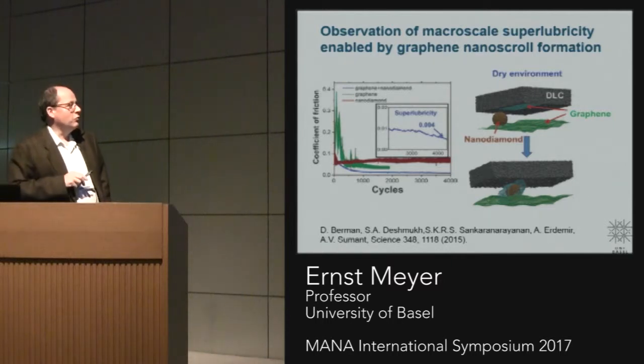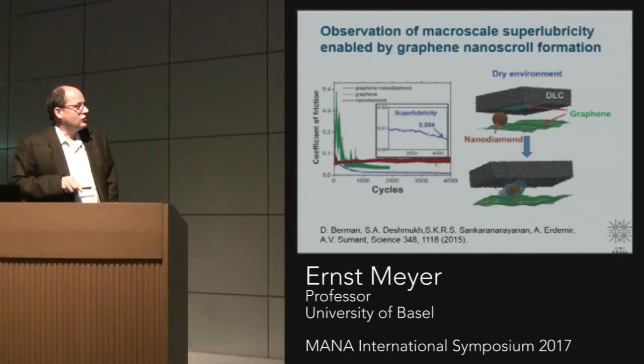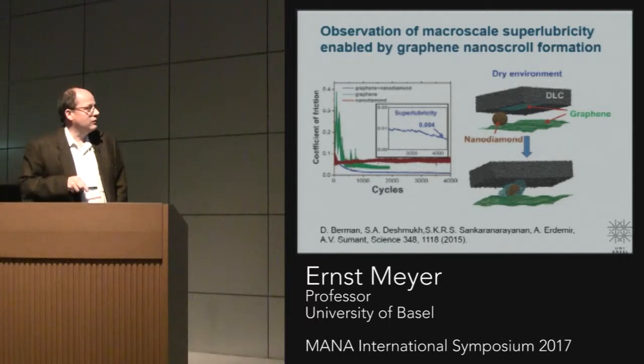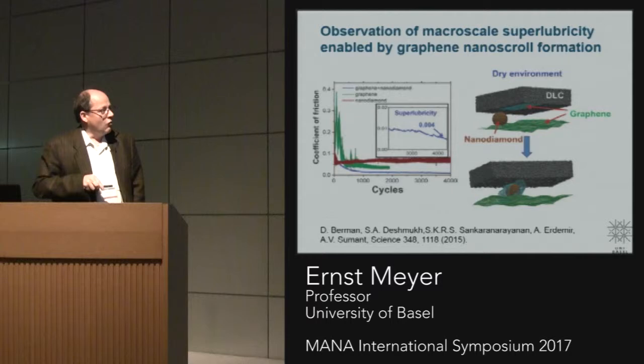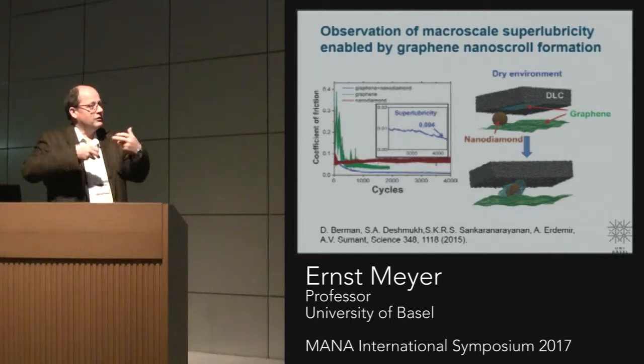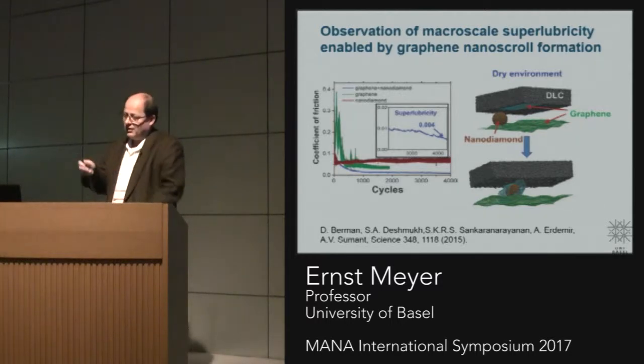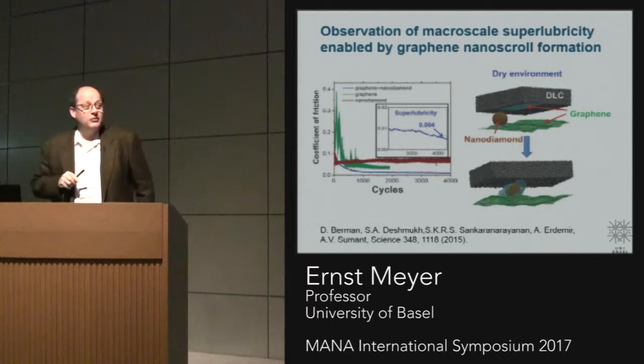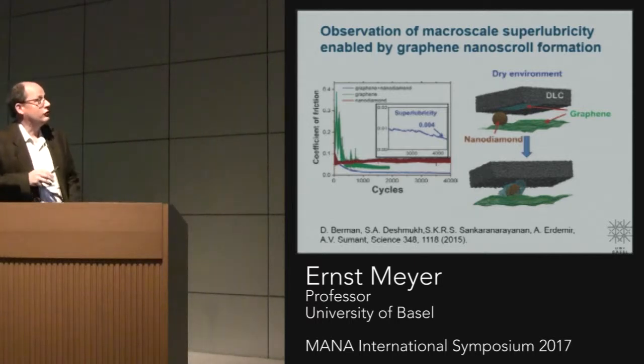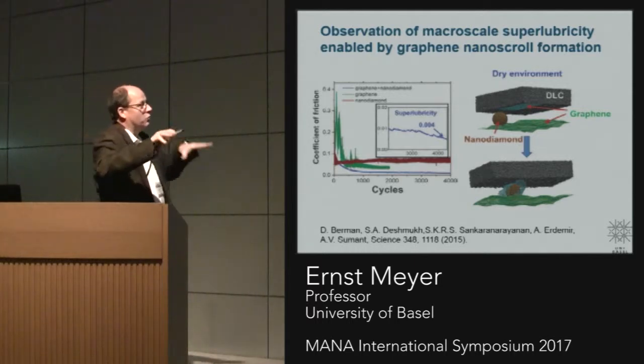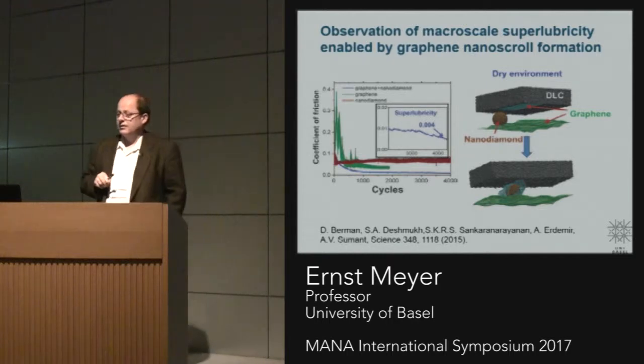So that seems to be promising, and what happens here is actually something quite special. What one thinks is that these nanodiamonds basically roll up the graphene, and that is then used like something which can reduce the friction of the whole contact by supporting this slider.